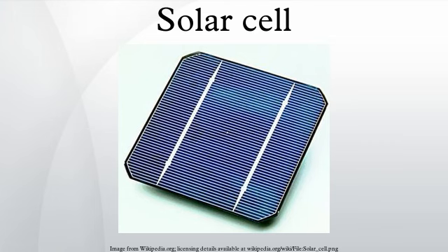Manufacturers of wafer-based cells responded to high silicon prices in 2004–2008 with rapid reductions in silicon consumption. In 2008, according to Jef Poortmans, director of IMEC's organic and solar department, current cells use 8–9 grams of silicon per watt of power generation, with wafer thicknesses in the neighborhood of 200 microns.